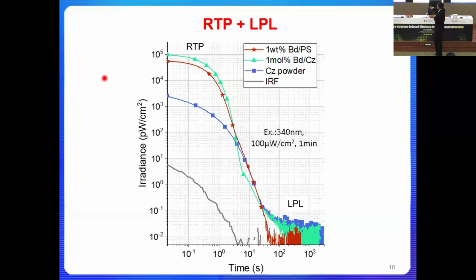But of equal importance is if we are doping this molecule into the polystyrene at the platform. That means we're actually dispersing the dopants into the polystyrene, right? We will also be able to get a very high phosphorescence. So that's an important experiment to show that we're not able to capture the optical signal, not because they don't show room temperature phosphorescence. It's only because we are not able to create the environment to make sure that we're able to induce the light emission as reflected by the molecule itself.